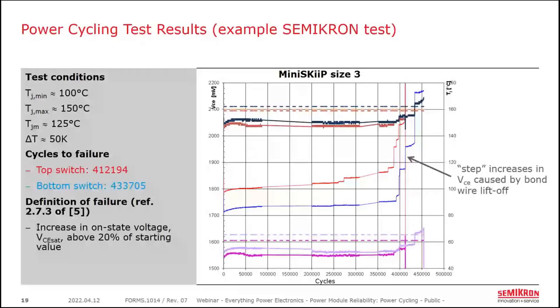But the voltage drop is also used as the criterion to determine when a device has failed the test. The criterion is actually a 20% increase in the forward voltage drop above the starting value. In this test, we can see a failure beginning to happen in discrete steps where the voltage drop is jumping up very suddenly towards the end of the test. What's actually happening here is individual bond wires are lifting off, or the heel is cracking, it's breaking, and you're getting these 100 millivolt jumps in the voltage drop as each bond wire breaks off.